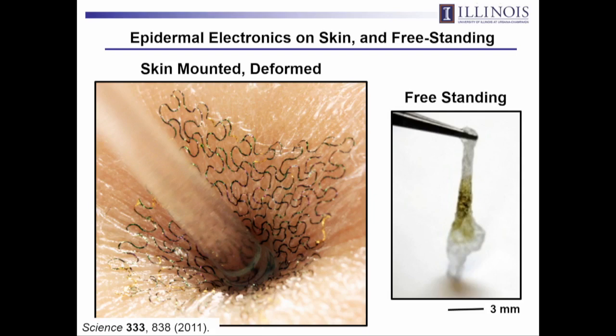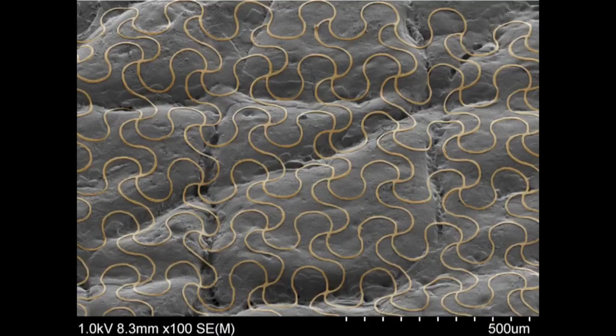And furthermore, because the mechanics are so soft, there are very small interface stresses that develop between the device and the skin. So even without robust adhesives or penetrating pins, straps, or glues, these devices can stay adhered to the skin just by van der Waals forces alone. And of course, if you grab them by the edge, you can peel them off, and that's kind of what it looks like. I mean, it's very sort of biological-like or skin-like in its mechanics. It's so soft and floppy, it doesn't even support its own weight, as you can see there.